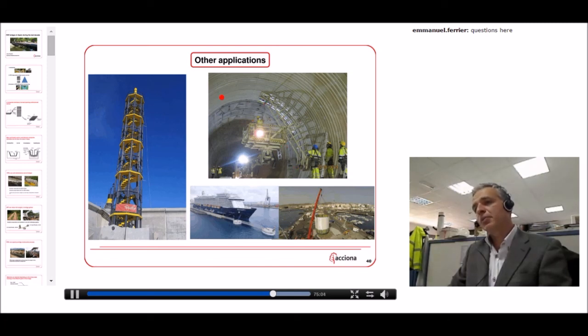The main challenge here was the fact that complying with the fire requirements in a railway tunnel was very difficult. These panels were manufactured by pultrusion. And here you see another application in the Canary Islands: the prolongation of a jetty using 2 glass fiber caissons that were filled with sand, and they work as dolphins for the mooring system of the ships. These are the last 3 applications of FRP here in Spain in which we participated.